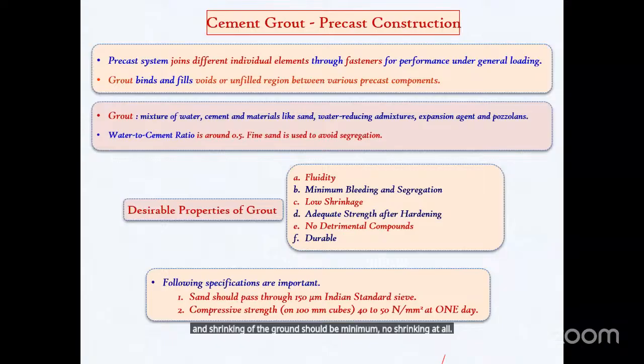And sufficient strength after hardening. Whenever you use this, it should reflect the original characteristics of the structural component, with no detrimental effect. And of course, it should be as durable as the precast element. Therefore, all these characteristics can be achieved using cement grout. Now, all precast segmental construction uses this cement grout.